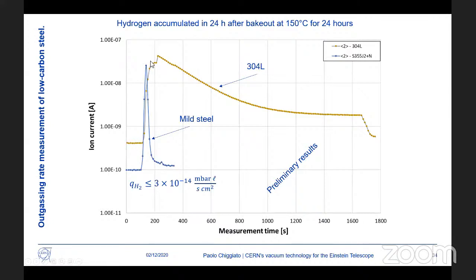While the peak of the austenitic stainless steel is very large and with a long tail. So integrating all that, it gives an outgassing rate for the mild steel which is lower than 3×10^-14 millibar liter per second per square centimeter, which is at least 2 orders of magnitude lower than the one of the as received 304L.